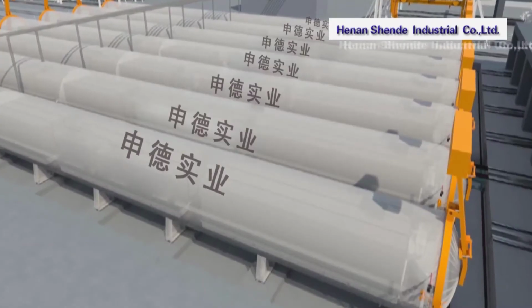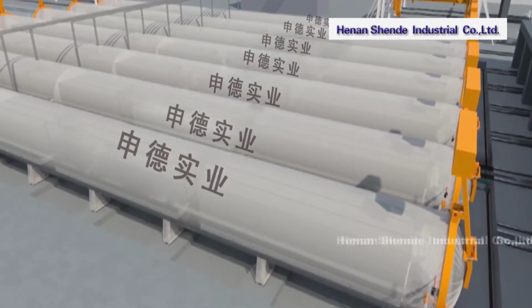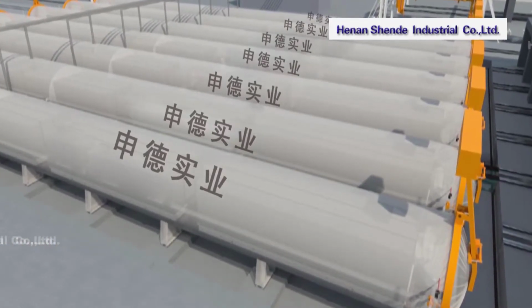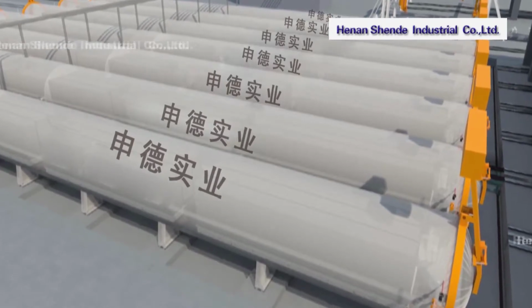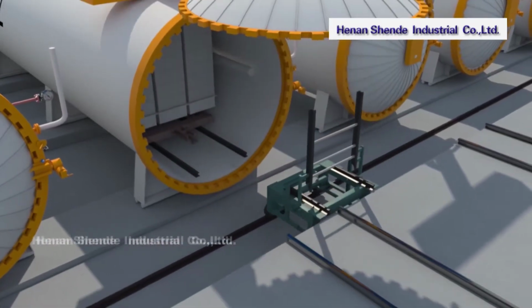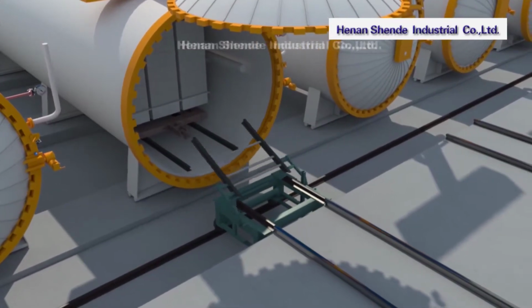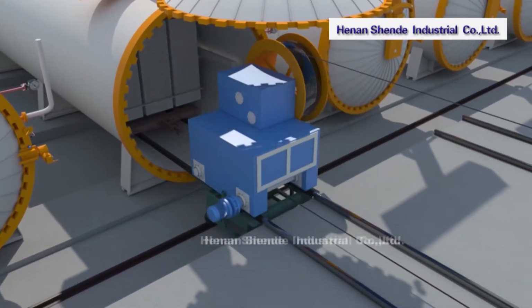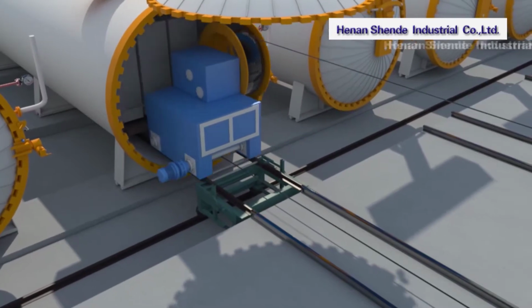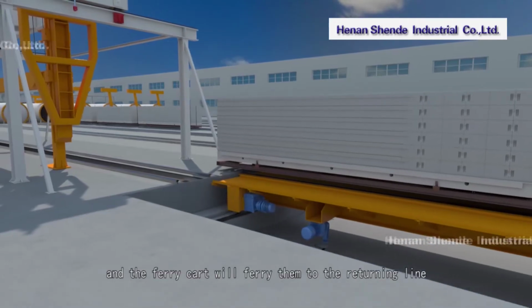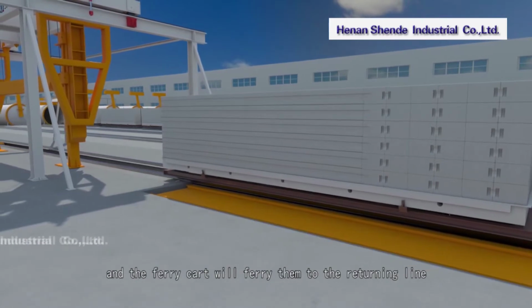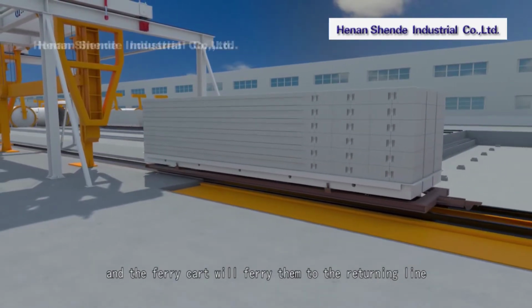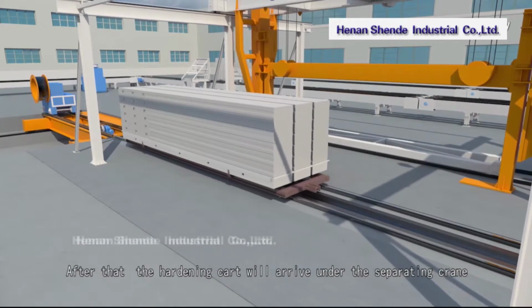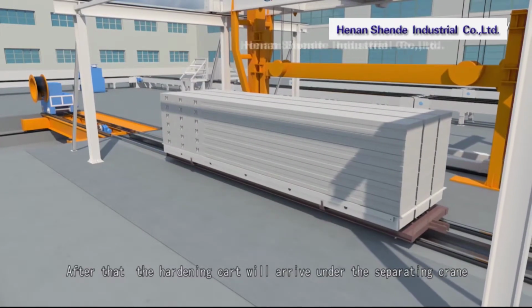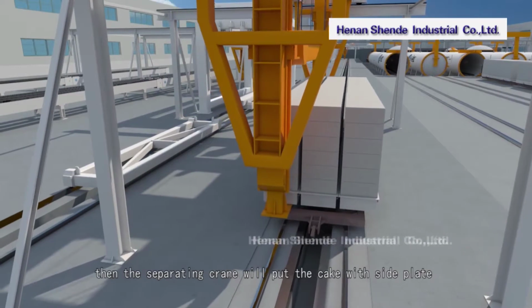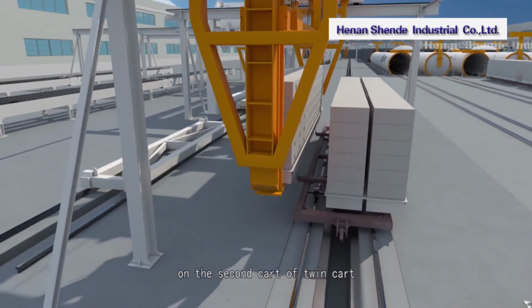And then, the cakes will stay in autoclave about 8 to 11 hours for curing at high temperature and pressure. After finished steaming, the traction car on the ferry cart will pull out the hardening cart with cakes to the ferry cart. And the ferry cart will ferry them to the returning line. After that, the hardening cart will arrive under the separating crane. Then the separating crane will put the cake with side plate on the second cart of twin cart.